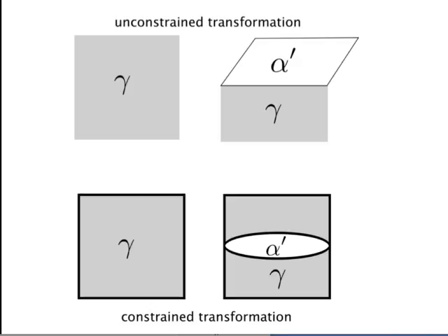So we can get what's known as single interface transformations. That means you have a single crystal, and then the interface is moving, and it accomplishes a deformation. And you basically adopt the shape of the crystal plus the deformation caused by martensite. So in most cases, we are looking at polycrystalline materials. So this is surrounded by lots and lots of other crystals, and therefore it forms as thin plates.